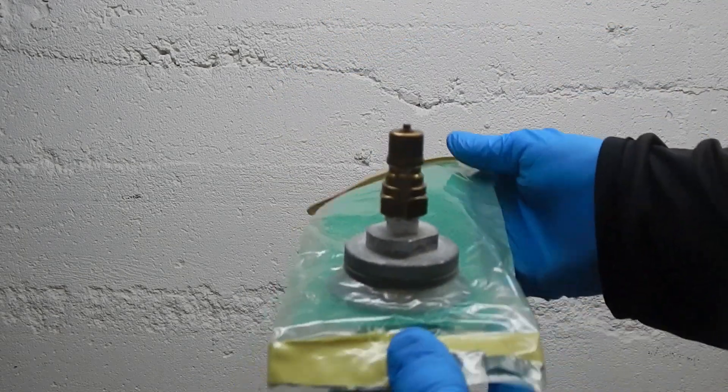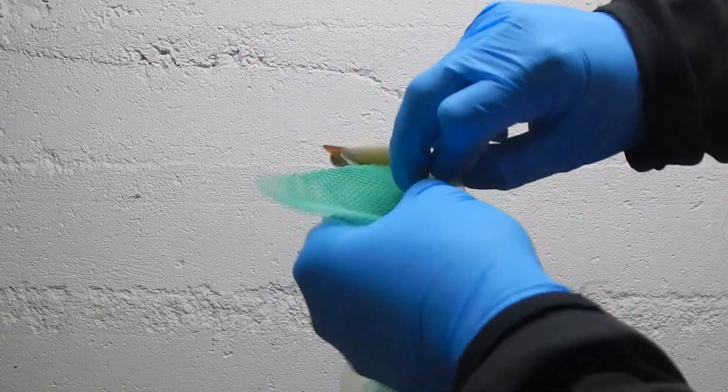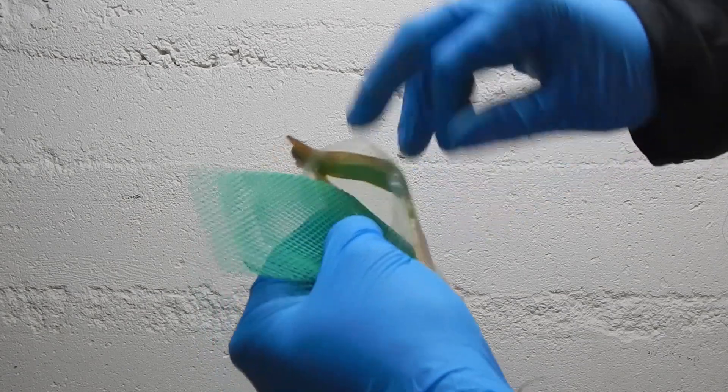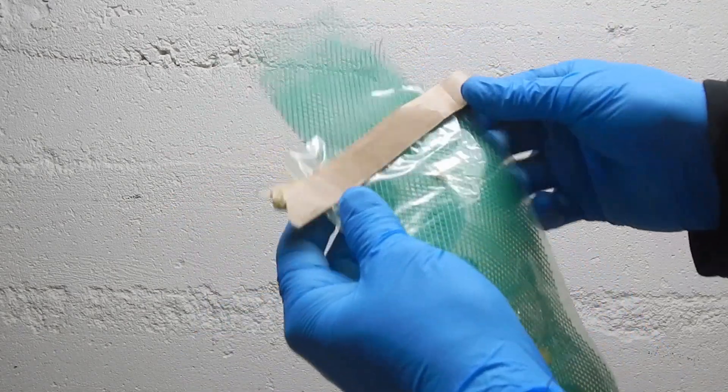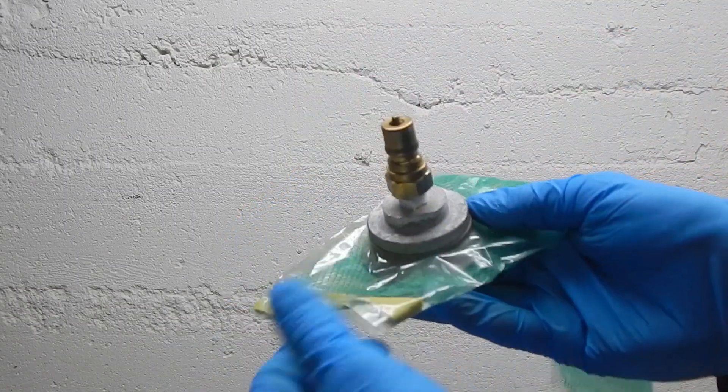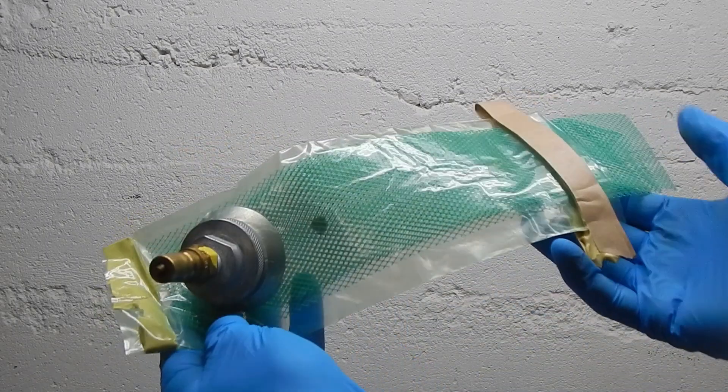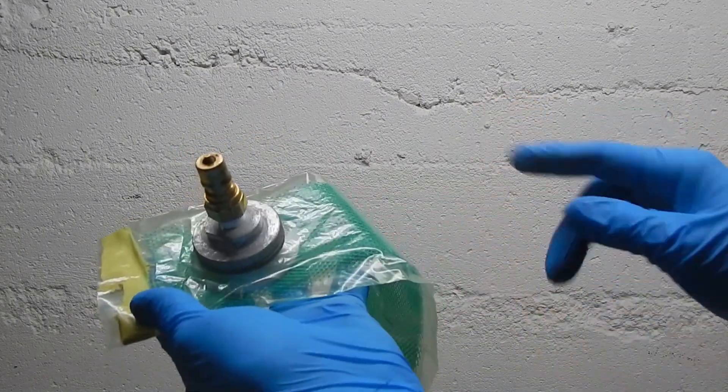One more way to protect your vacuum connectors. Here's a piece of tube bag assembled with infusion mesh inside, some sealant tape, with the vac connector way out on the end. It's a great way to handle situations where you don't have room for a fitting under your bag, or you want to get the fitting away from the resin.